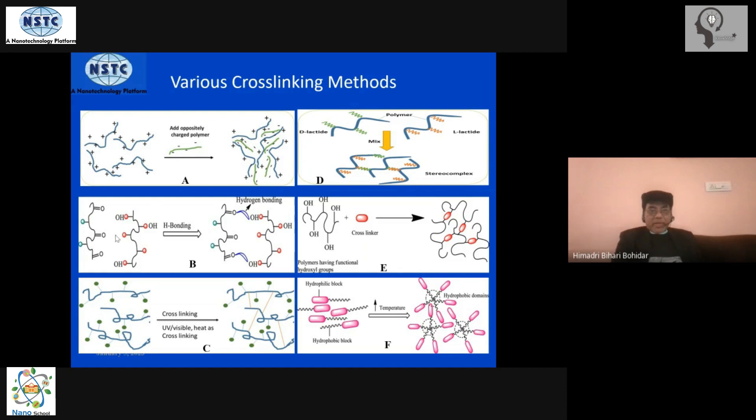Then they will beautifully form hydrogen bonds and go into a network structure. Third one is cross-linking through high-energy radiation—either UV radiation, gamma ray, or X-radiation—which creates binding sites in the materials, and then the polymers get cross-linked by joining each other on the binding sites.